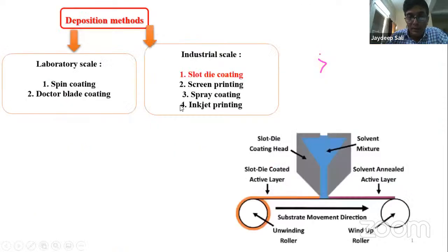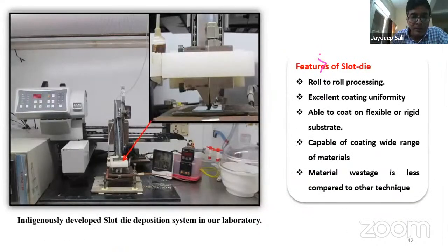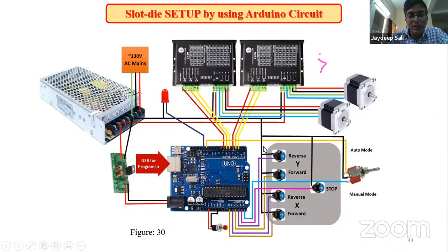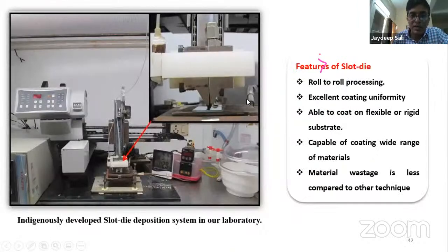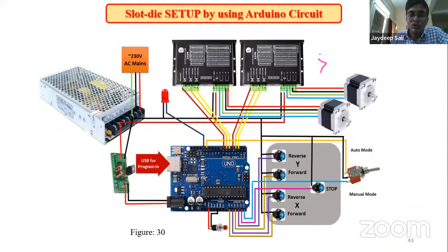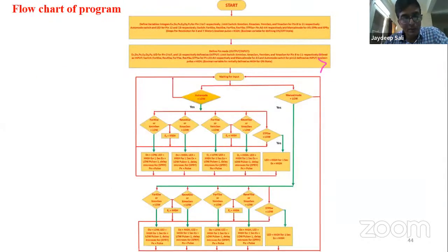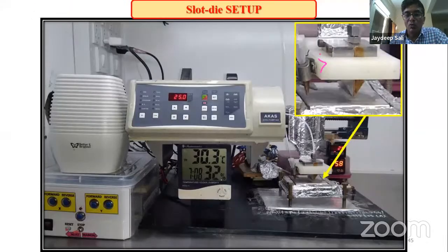So I will directly go to the last result. This is the thin film deposition system, that is a slot die deposition system, that we have indigenously fabricated in my laboratory. This system is being used for the fabrication of perovskite thin films for solar cell application. The XY motion of this slot die head is controlled by an Arduino circuit, a very simple circuit that my students have fabricated with the necessary software. With this, we can control the XY motion of this head, and using this, we can prepare thin films of the perovskite material.